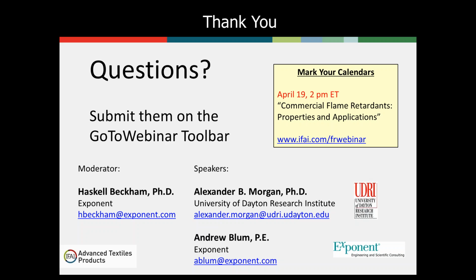Go figure. So what's interesting about this is that those reduced ignition propensity cigarettes that are currently on the market are the only ones you can legally buy. And yet in the TB 117 standard, they use a NIST standard cigarette that doesn't have those little bands, so it burns and smolders differently. There's a lot of political issues going on with this California TB 117 standard. The focus of that standard appears to be that they feel that cigarette ignition is the primary fire risk for seats, not open flame, and therefore they wanted to change the test to push their particular belief.